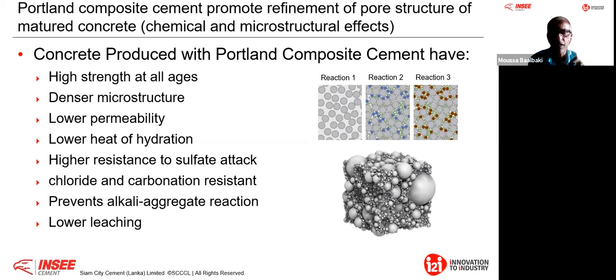But the problem is, if you continue to have leaching, the pH goes below 7, suddenly your calcium silicate hydrate is not stable anymore. Therefore, you start to lose strength. That is why some water towers can collapse, some balconies can collapse, we think it is a corrosion of the reinforcement. No, it's not only the corrosion of the reinforcement, it's because we went to a very acidic pH. Even your CSH, your calcium silicate hydrate that is responsible for the compressive strength by itself, gets reduced. Okay, that is really a very important engineering property.